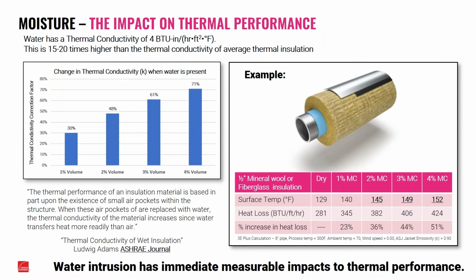Now, looking at the impact of thermal performance, I think anecdotally everybody knows that this is what happens. That water is going to conduct more heat, and like the example that we had earlier. But if you look at water's thermal conductivity, it has 4 BTUs per inch per hour, square foot, Fahrenheit degree, which is about 15 to 20 times higher than what you would typically find with most common insulations, whether it's a foam plastic or fibrous or cellular glass.